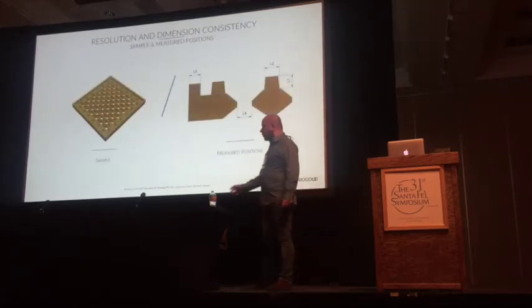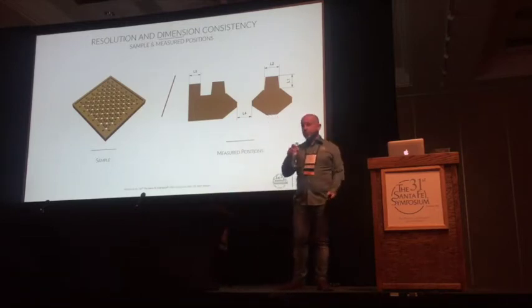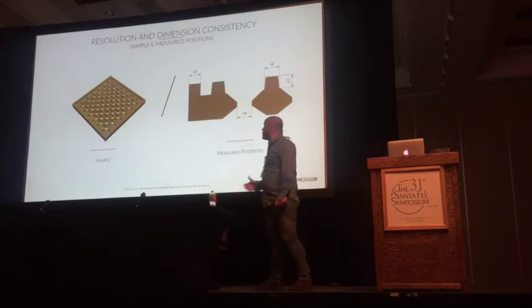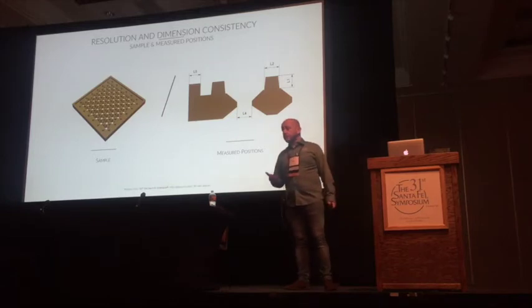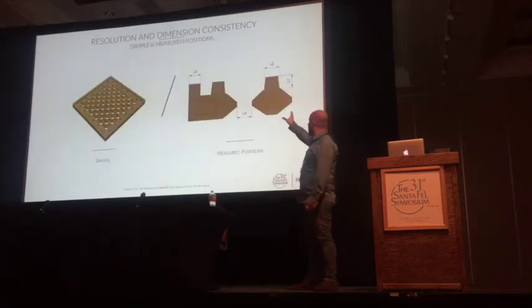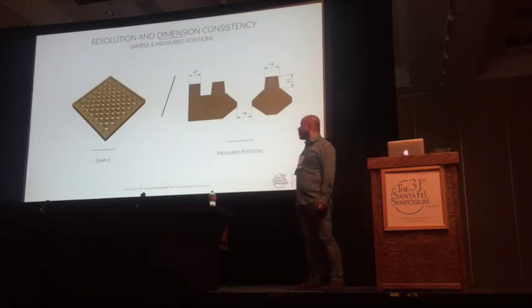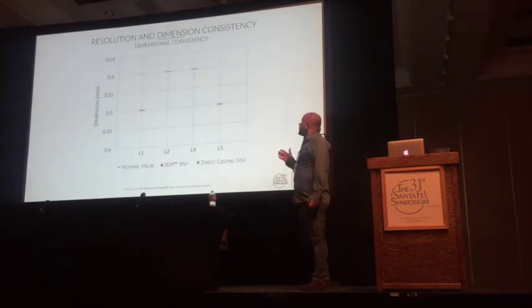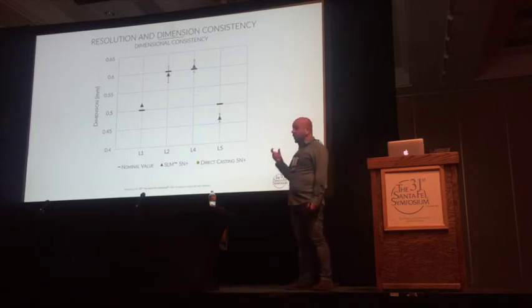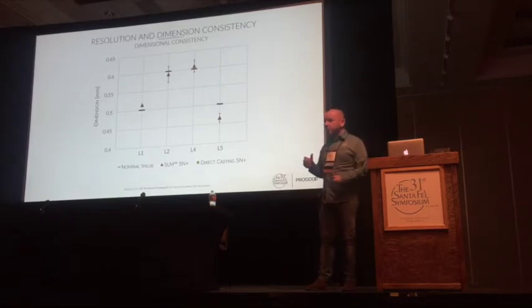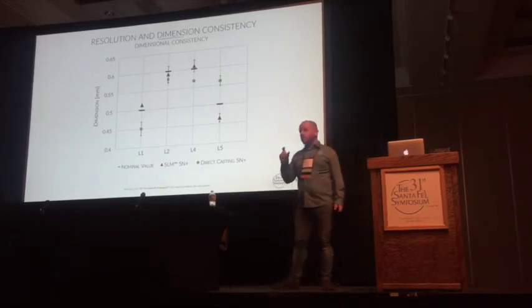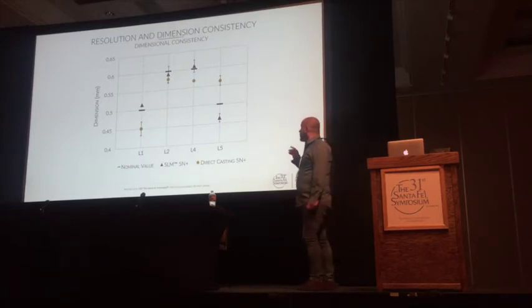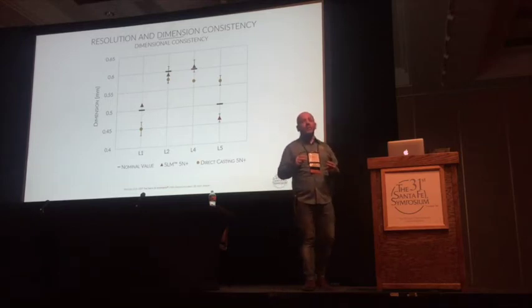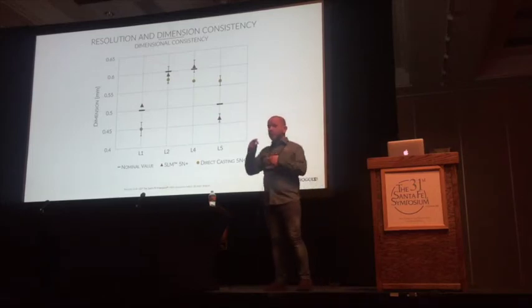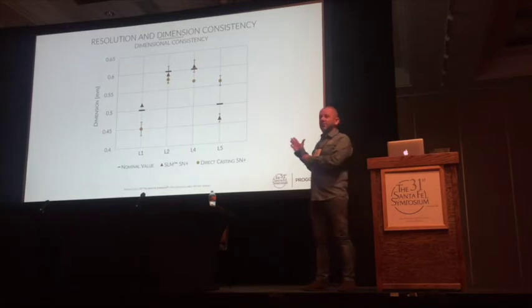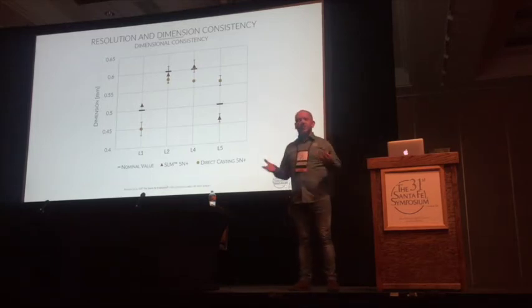Then another thing that we were collecting from a paper presented some years ago was the dimension consistency. We were measuring this part where the stone is going through. That one was the sample, and those are the nominal values. In the case of 3D metal printing, we had a standard deviation of 3-4 microns, plus or minus. And in the case of direct casting, we were in a similar condition. The difference was that in 3D metal printing, the nominal value was in the range of the standard deviation in 2 cases. But I don't see really any advantage here because even casting is quite good. So the value is not here.